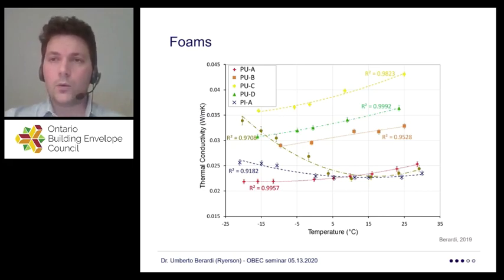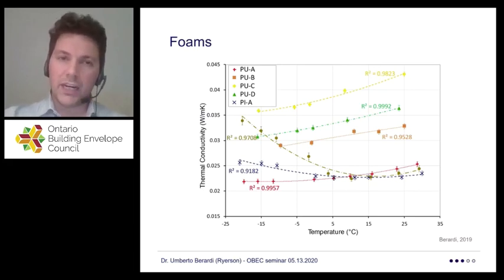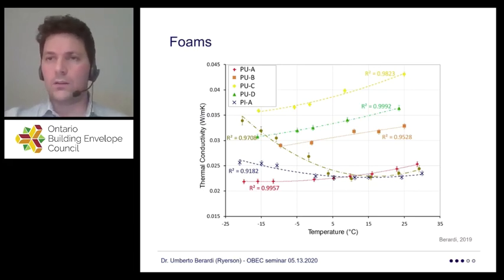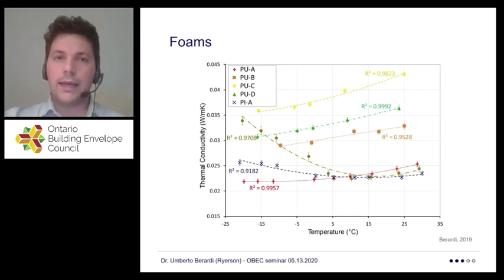But what actually is quite clear for a lot of people is that a lot of these foams have kind of gases, or some of the foams, especially old generation of polyisocyanurate. Okay, so this is not necessarily a problem that you find in any of the new products. It's often a problem that you find consistently when your roofs were built a decade ago, for example, and some of the new polyisocyanurate may still have this trouble. And the trouble is basically that some of the blowing agent we have been using, at the end of the day, they are trying actually to condense.